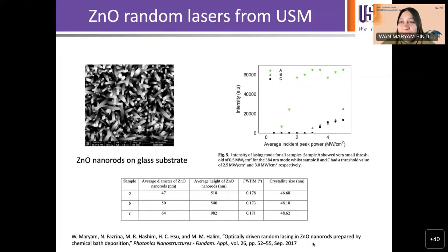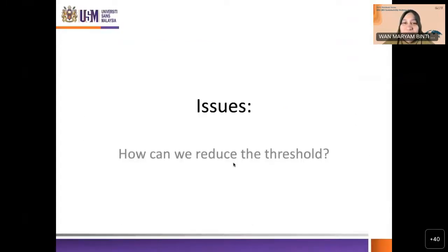So when we collaborated with National Cheng Kung University, we started just by looking at zinc oxide nanorods on glass substrate. It was prepared by a simple method of chemical bath deposition, and we observed that we have a low threshold when the size is roughly less than 50 nanometers in diameter, and the height is roughly half a micron. Okay, the problem is it's still quite high. 0.5 megawatt per centimeter squared is high, right? So the question that we have is, can we reduce this further? Can we bring the threshold down for it to become useful devices?